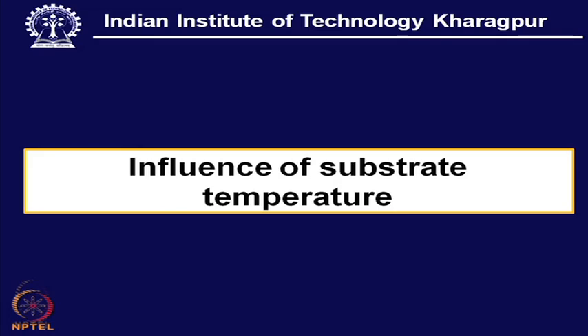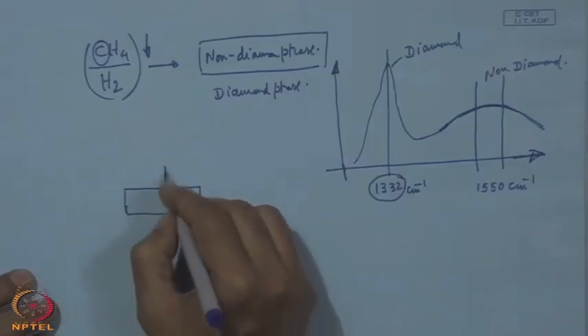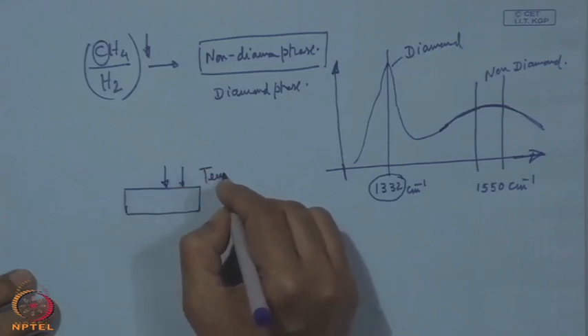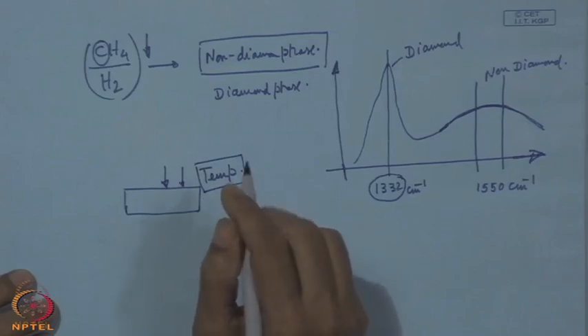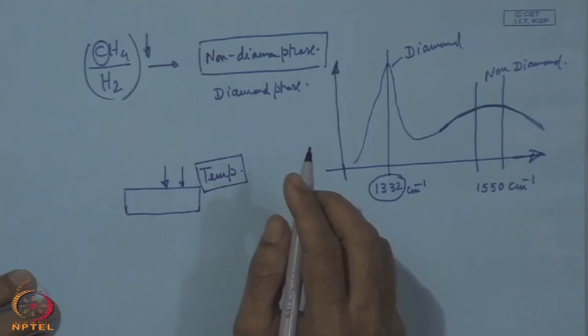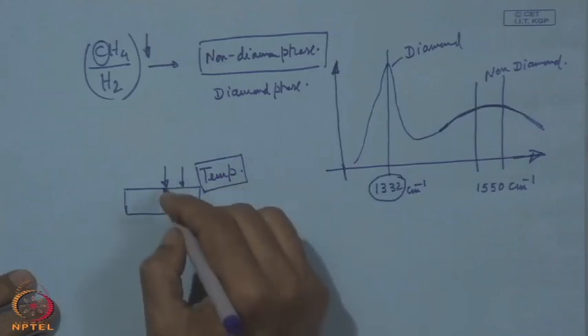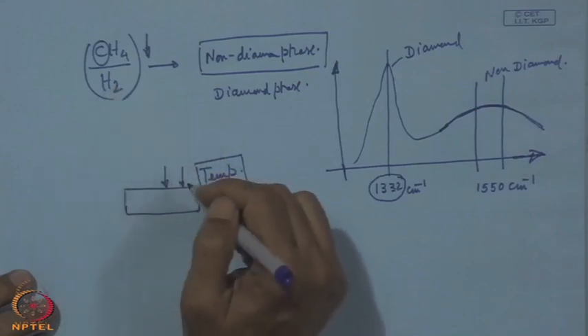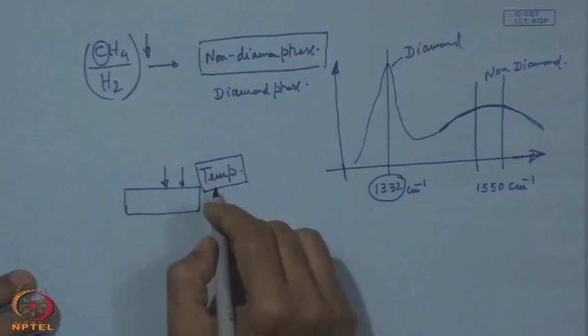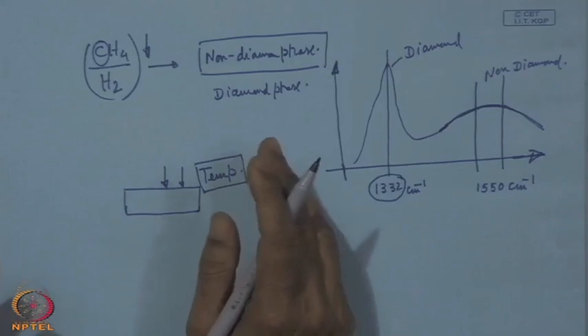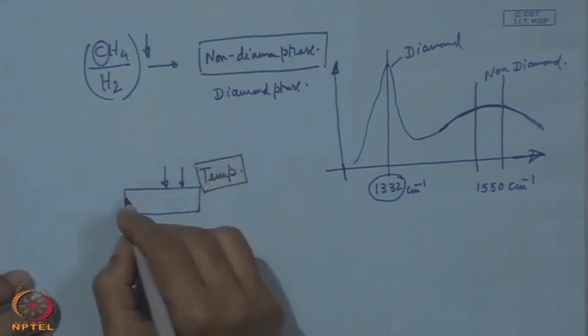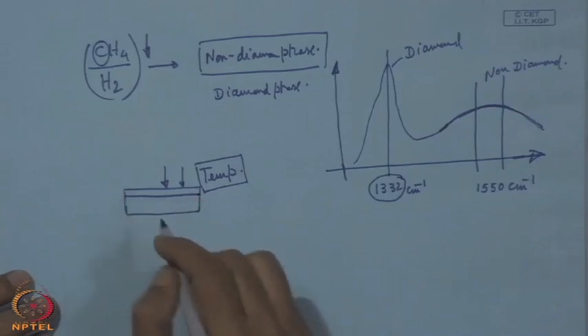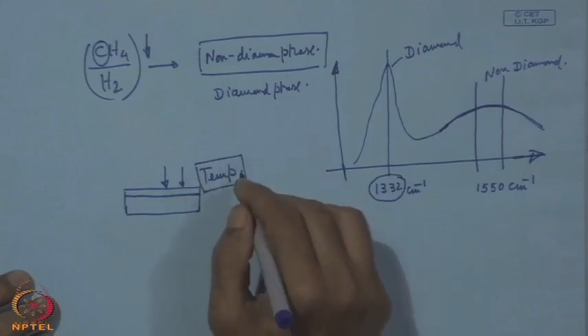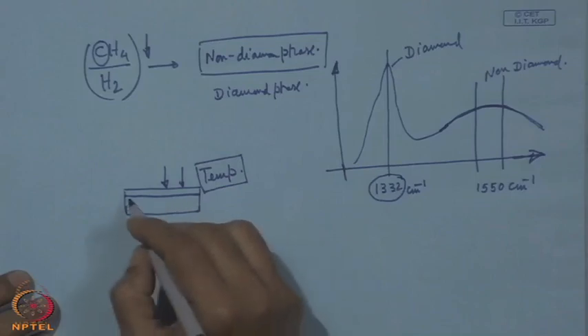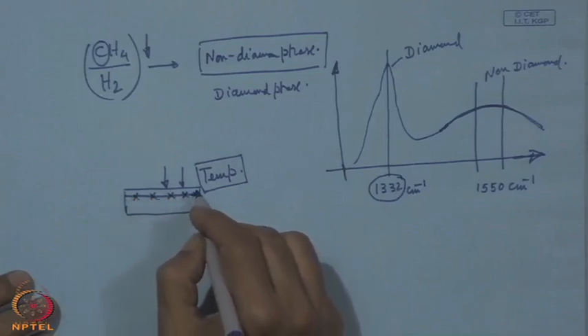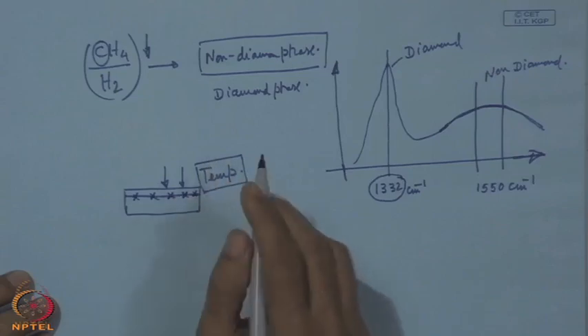Influence of substrate temperature. Now, this substrate temperature, in one way it helps in the nucleation and growth of diamond, but at the same time it can also be counterproductive if we have too high a temperature, where it will be thermally activated and then by this hydrogen we can also have etching of diamond. So this temperature should be chosen properly, somewhere between two extremes, to have diamond with reasonable growth. And more importantly, if we have too high a deposition temperature, like in any CVD, we may also have an adhesion problem because of the stress discontinuity. So this point should also be looked into.